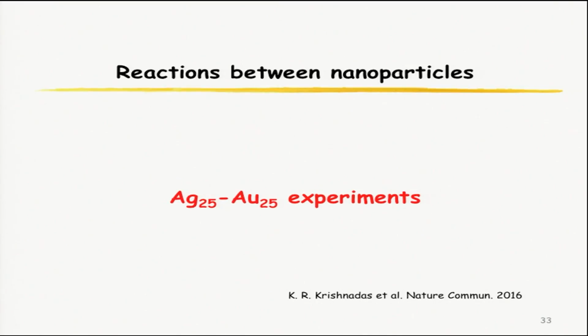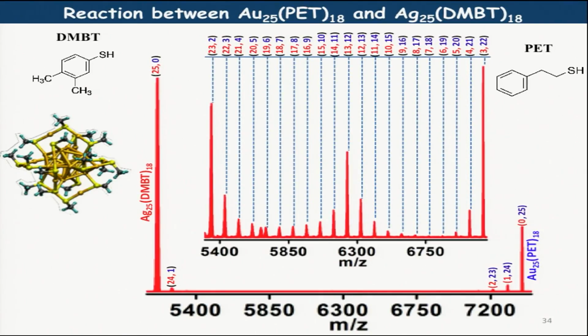And you see, gold 25 will give you a mass peak, silver 25 will give you a mass peak, and this is what I'm supposed to see. I'm supposed to see a gold 25 peak and a silver 25 peak. Silver is less in mass, so you are supposed to see two peaks. But just after mixing, very many new peaks come, just because one gold atom goes into the silver and one silver goes into the gold.